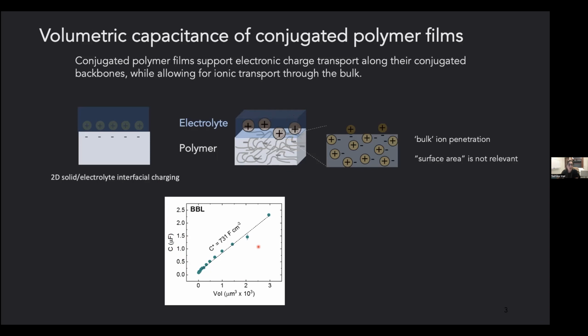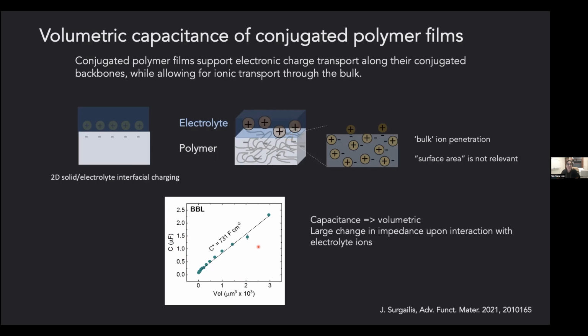So conjugated polymers are volumetric capacitors. And this is quite an important property because this means when there's a biological event that takes place, which causes a flux of ions in the electrolyte, now your material will be very sensitive to these changes because its conductivity, its impedance, its capacitance will change dramatically as the ion and electron interactions take place in the bulk of the film. So we design biosensors such that the biorecognition event changes the ionic flux, and we can see this via an impedance change in our conjugated polymer film.